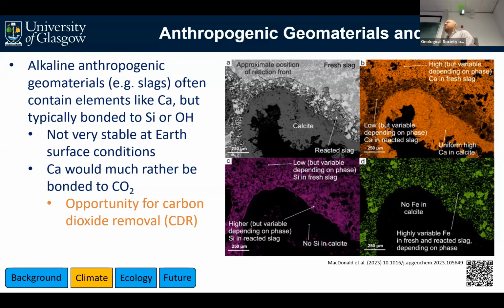And I mentioned earlier that a lot of these anthropogenic geomaterials are alkaline in their composition, so they're high in elements like calcium. But they're in these slightly weird, unusual minerals, and that calcium in something like a slag is typically bonded to elements like silicon or a hydroxide, OH anion, and they're not very chemically stable at Earth's surface conditions. Kind of not a surprise because they're formed in a furnace at thousands of degrees. But if you then just dump these things on the Earth's surface, they're going to undergo chemical changes.